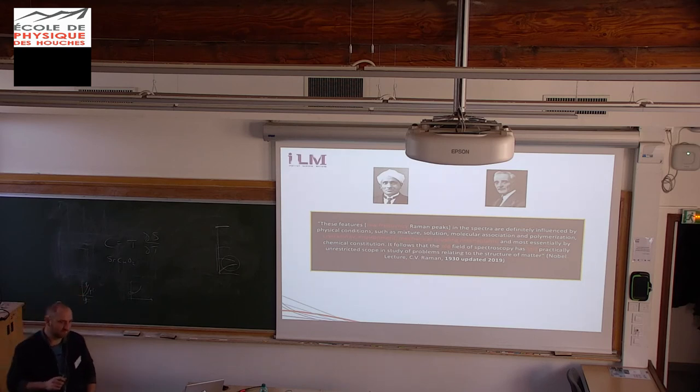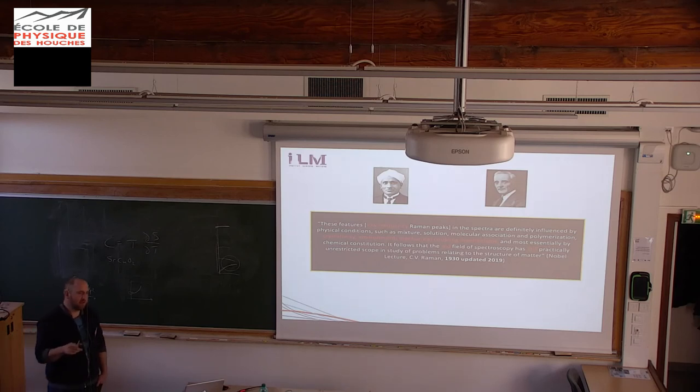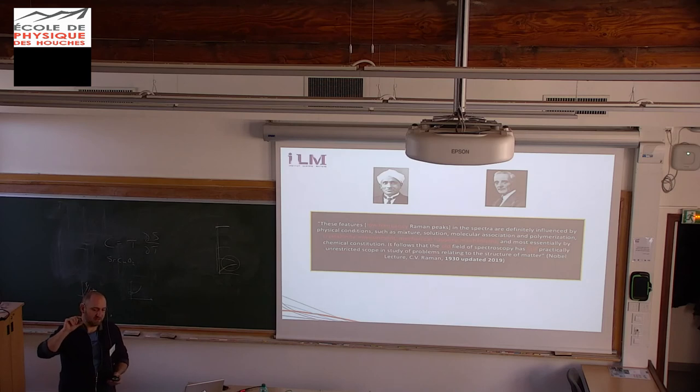Yeah, exactly. Some people at the beginning tried to consider that you have a continuous medium, that ligands simply have a different acoustic impedance. But doing that, you are not able to reproduce these results, because you have to consider that acoustic waves propagate inside the ligands, but it's not enough to interpret what we have observed. Some people have done that on spherical nanoparticles, and it was working. But if we check a little bit what they are seeing, they are seeing the vibration of the shell of ligands, that's right. But it's a bit different from what we are seeing here in that case.